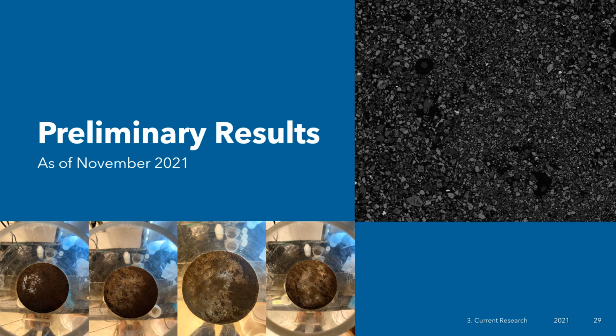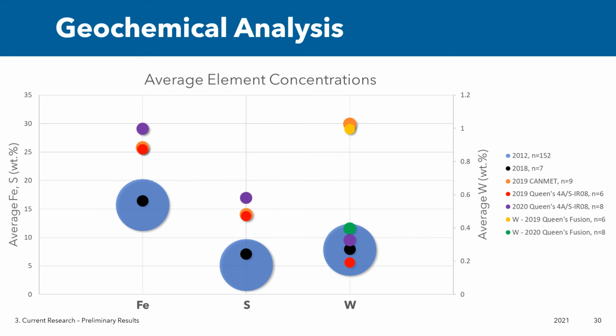Results as of November 2021 include geochemical analyses, mineralogical data, water content, and oxygen consumption trends. To start the characterization work, subsamples from the 2019 and 2020 samples were analyzed. Here the results are being compared to previous analyses conducted in different years to assess the heterogeneity of the Cantung tailings. This figure is showing the average element concentrations for various years, with the bubble size indicating how many samples were analyzed. In 2012, 152 samples were taken from multiple points within TP3 and were considered to be representative of the entire tailings pond composition.